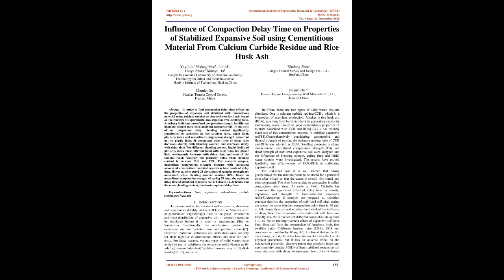Based on unconfined compression strength of curing 28 days, the optimum delay time of stabilized expansive soil is between 12 to 36 hours, and the more blending content, the shorter the optimal delay time. Keywords: delay time, expansive soil, calcium carbide residue, rice husk ash.